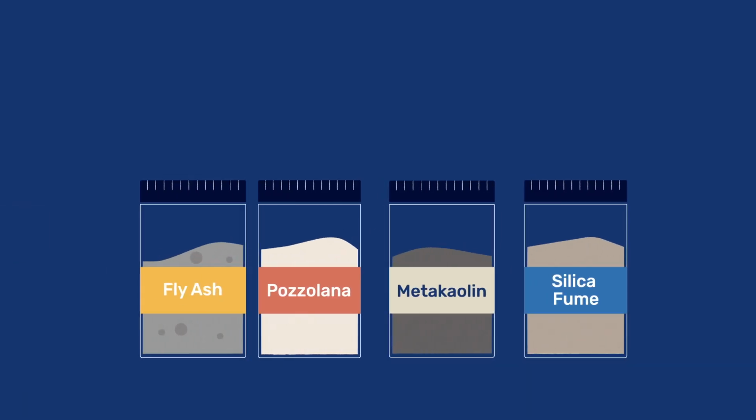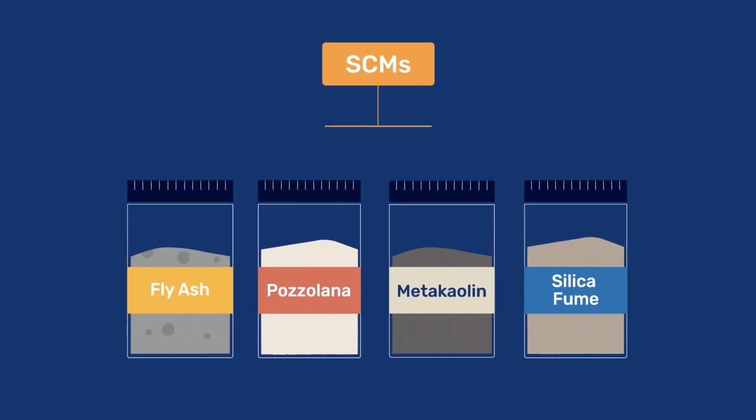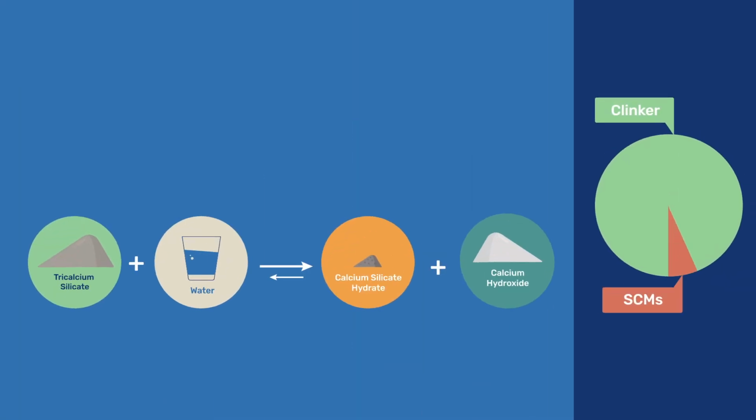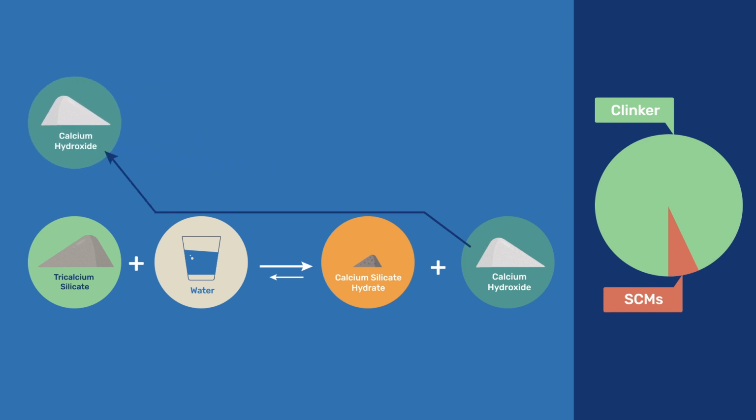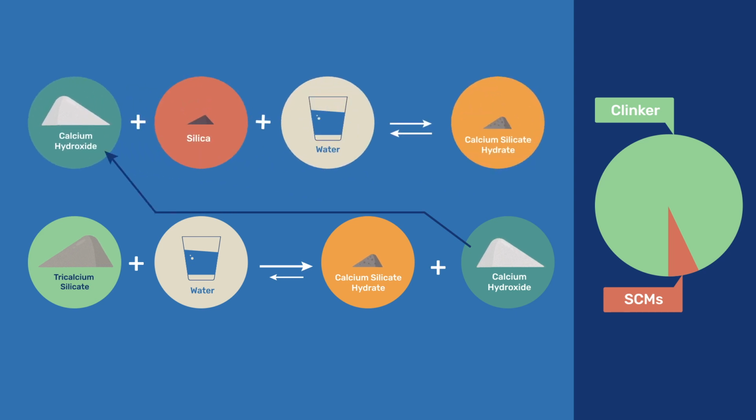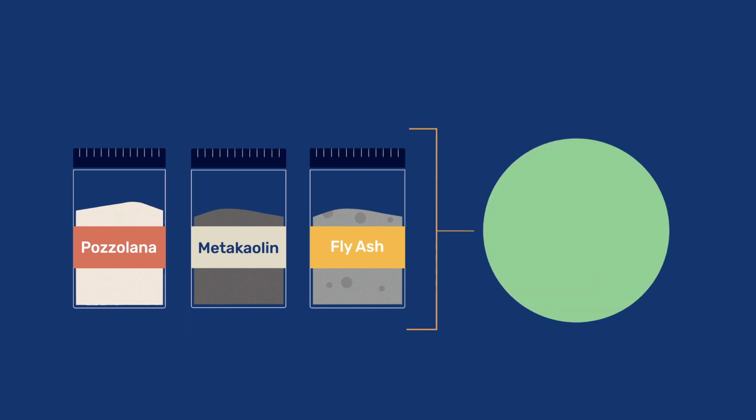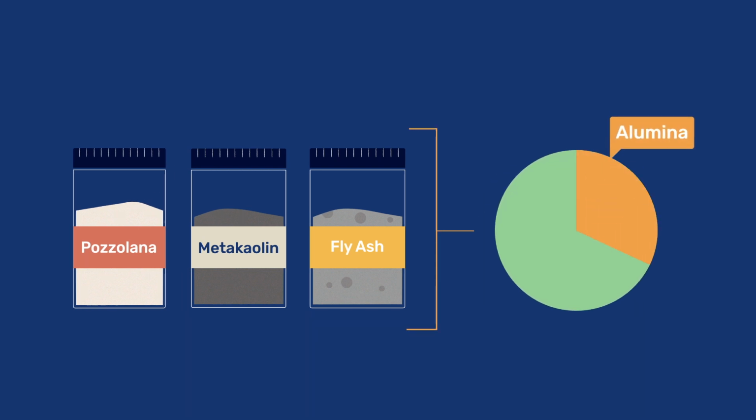In conclusion, the pozzolanic reaction concerns many supplementary cementitious materials to various extents. It takes place between the calcium hydroxide produced by cement hydration and the amorphous and/or poorly crystallized silica-containing phases of the SCMs. This puts an upper limit to the degree of clinker substitution above which SCMs will only partially react. However, many SCMs also include aluminates, which offer additional reaction routes, as discussed in our subsequent video.